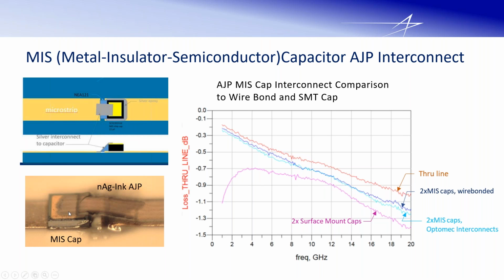So you have your capacitor, printed dielectric, again, the NEA 121, and then the ramp. So on this third one, we're trying to make this ramp extend out a lot less. So it's going to be more conformal, just a little ramp down to the pad, really shorten up that length, minimize the material, and we're trying to get the printed interconnect close to just a straight through line. So if this was a through line without any capacitor, this is what you get. So this would be considered as best that you can do.